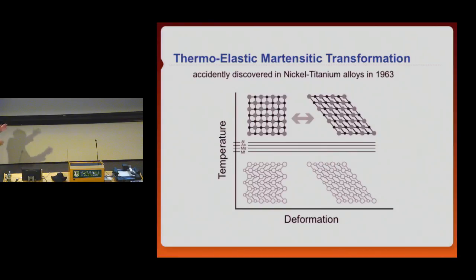And they formed these, I mean, those are the anecdotes. They said they rolled the sheets and stuff like that, and then they formed the hull of the ship, and then when they started welding, these formed sheets would all go back to their rolled and straight condition, and they wondered what it was, did some further experiments, and found this martensitic transformation in nickel titanium. And from now on, I will call this material Nitinol.